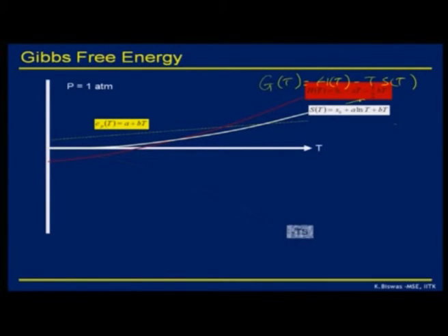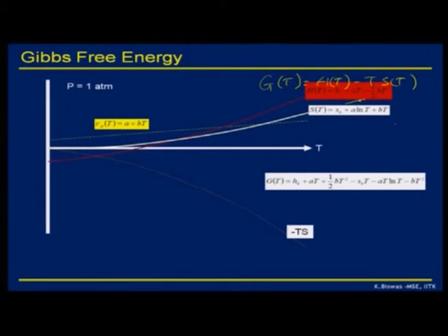So by that I can calculate minus TS, which will be like this, because if you multiply by minus T, this will be negative. So what is G then? G is H, that is AT plus half BT square plus H0, minus TS, which is this term, completely this term. So G is this. Now how will it look?